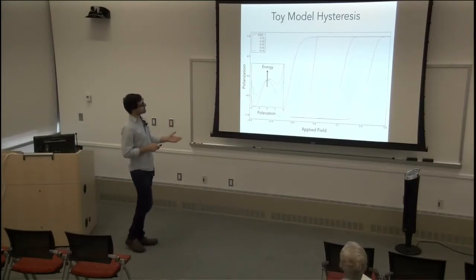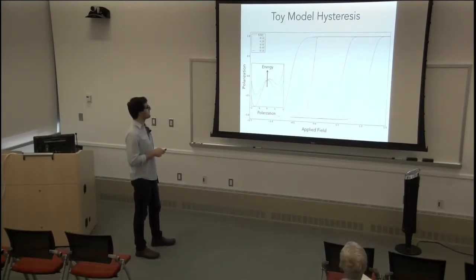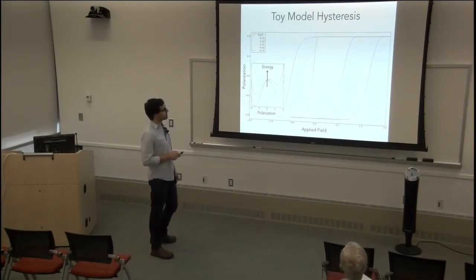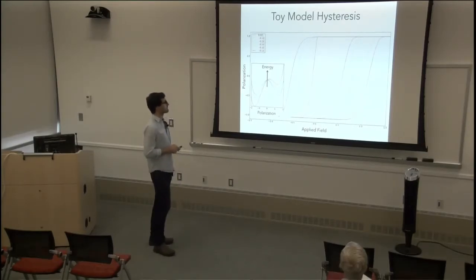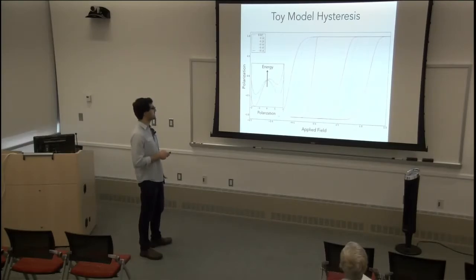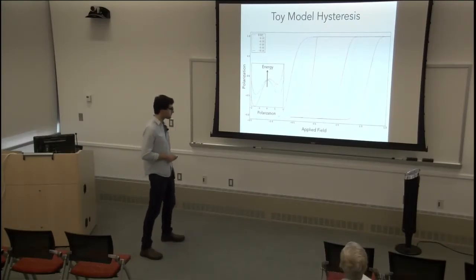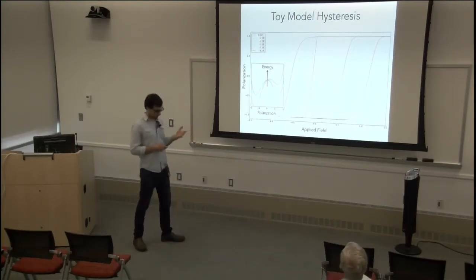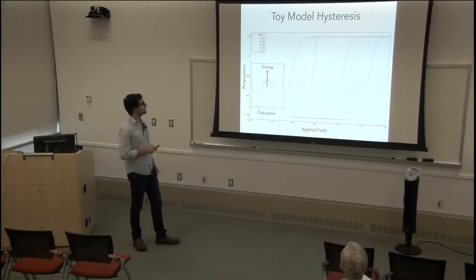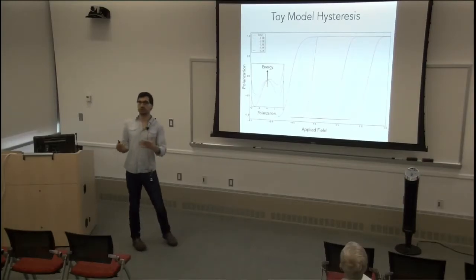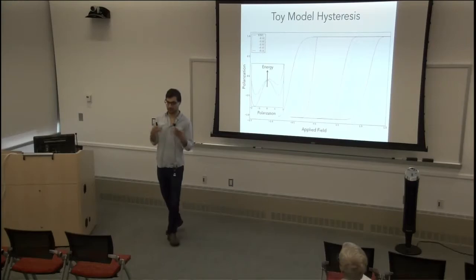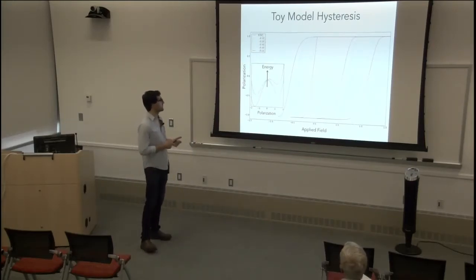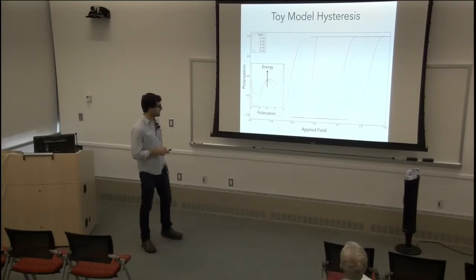Now I introduce asymmetry by hand into the double well, where the negative state becomes more energetically favorable and the positive state becomes less energetically favorable. You see that there's a shift to the right in the hysteresis. So there's a positive bias in the hysteresis. As you successively asymmetrize the double well, we have an understanding: what we want is to introduce something into the system that makes your double well asymmetric.